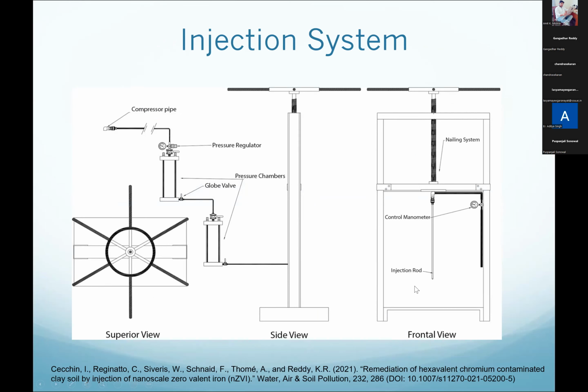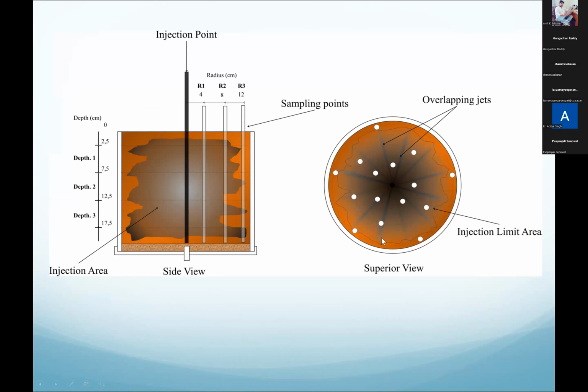So these guys created this experimental setup where you inject and distribute the iron. Here is the injection point, and it is like grouting, right? So you have nano iron particles. This is all in the vadose zone, no groundwater, and you inject it, and then you put these wells around, and you can collect the samples and see how much distribution you got. So here is their big tank, and after the distribution you core at different radii and different locations, and then collect the samples and test for nano iron concentration